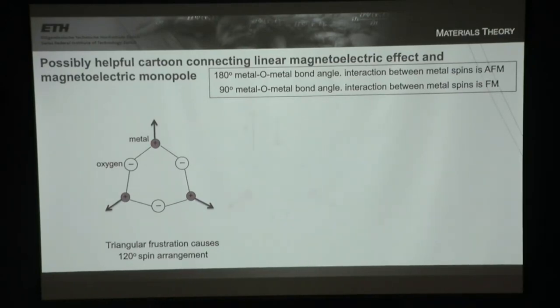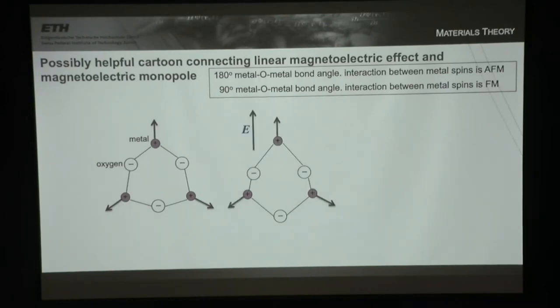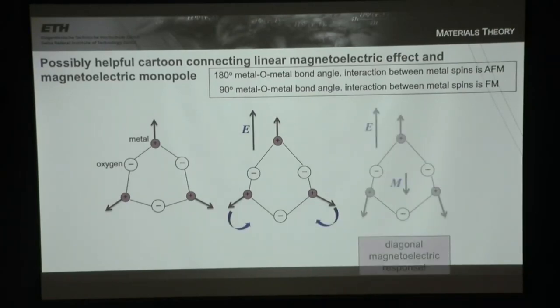So let's look at what happens when we apply an electric field. The positive cations shift along the field, and the negative anions shift opposite to the field. And so now this angle is very close to 90 degrees, and this one's even closer to 180. So these magnetic moments, if we go back to my rules, want to be ferromagnetic, and so they rotate and allow these magnetic moments to be even more antiferromagnetic. And so I end up with my electric field inducing a magnetization. So I have this diagonal magnetoelectric response as a result of the magnetoelectric monopole.